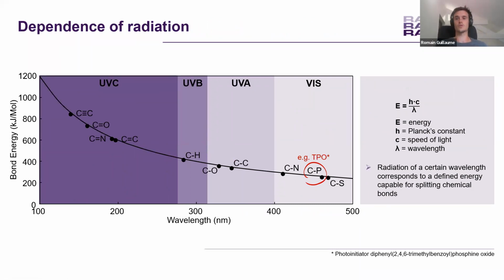Then, by continuing on the spectrum, if we look at the chemistry itself, we see that there is a big dependence on the radiation itself. So here you have a curve of the different molecule bonds we can try to break with the UV. So, for example, you have the TPO photoinitiator, which is in the red circle here. The energy needed to break this photoinitiator is around 450 nanometers. And if you look at the other photoinitiators or the other bonds, you can see that sometimes you will need a higher energy, which means a lower wavelength.